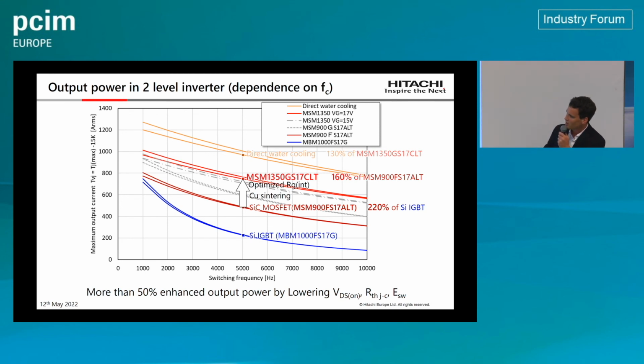And we are looking at the available output power, the maximum output current, benchmarked against the switching frequency of the converter. We can see that if we take a 5 kilohertz switching frequency and go from silicon to the original silicon carbide MOSFET, we can more than double the output current. This is the previous generation of silicon carbide. If we go to the new silicon carbide, we're more than 60% increase compared to the previous generation of silicon carbide MOSFET.